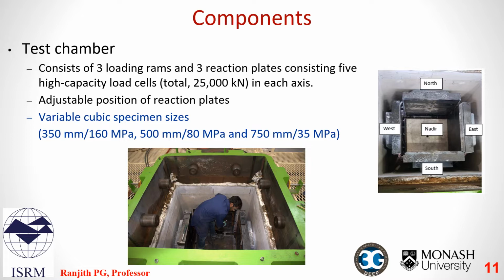As you can see, the reaction chamber itself is quite large, and we can change the setup loadings or reaction plates to accommodate 3 sample sizes, 350, 500 and 750 millimeters. We can go for even smaller sizes to accommodate very large stress over 400 MPa. As of currently, the smallest we can accommodate is a 350 millimeter sample subjected to 160 MPa pressures, and the largest specimen can be confined up to 35 MPa. On the right, you can see the spacer setup for smaller specimens that can be mounted for the loading pattern.